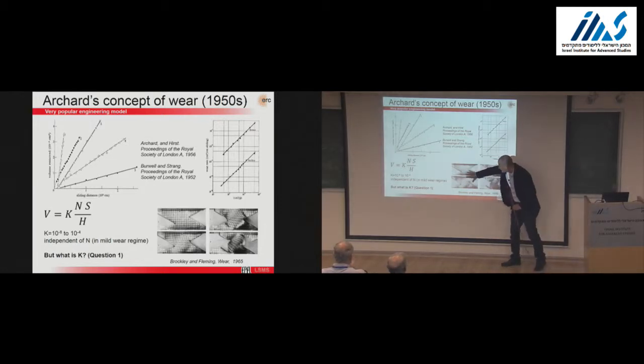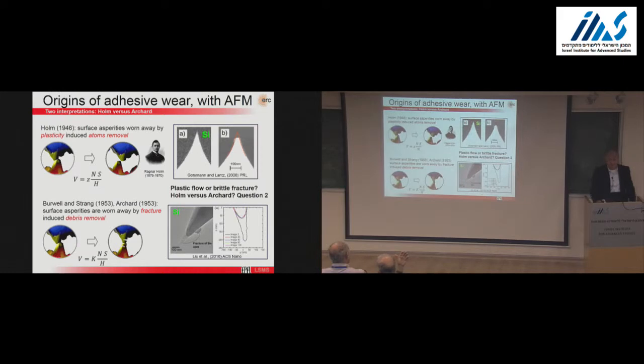I want to point out that there exist beautiful experiments from the 60s showing the debris formation process at large scales. So this bar scale here is 2 centimeters with a measure of deformation, and you see this shear apparatus that's basically loading this triangular junction and forming a debris. We'll try to replicate this with atomistic simulations later.